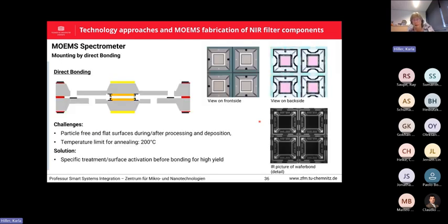However, the direct bonding is really challenging. If you know what direct bonding means, then you will understand this. You need a particle-free surface. Any particle will not allow a correct bonding. And this is not so easy after a lot of patterning steps, including sending the wafers away. And also, due to this optical layer stack, we have a temperature limit for annealing of only 200 degrees.